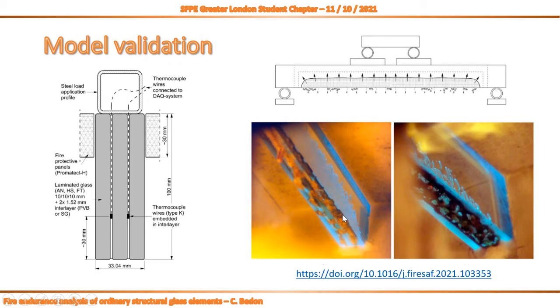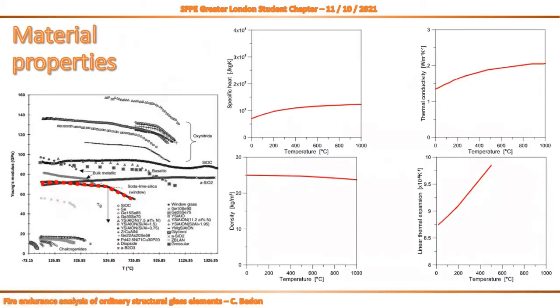For the numerical study, we did take advantage of the experiments on full-size beams, but also of some literature data related to material properties. First of all, the Young modulus and its sensitivity to temperature, but also some important parameters that usually we can skip for mechanical considerations in cold conditions. So the variation with temperature of specific heat, thermal conductivity, linear thermal expansion, and density.